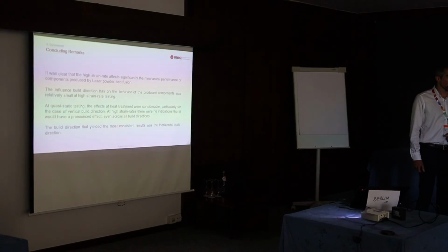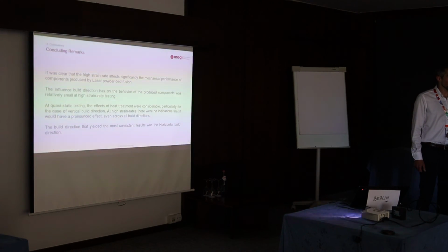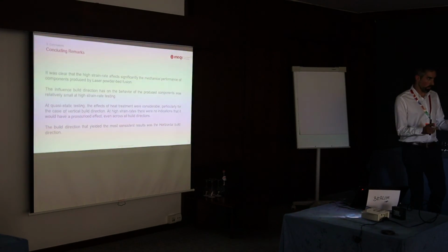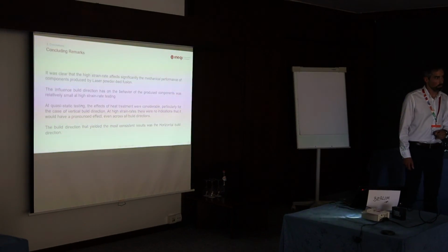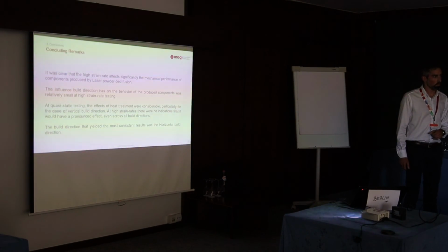Thank you. In my opinion, another way to really look at the strain rate dependency of a material is to do a simple tensile test with a machine where you can vary the strain rate during the test. So you can really see the jump on the same material. Then you eliminate a lot of factors with different samples. But would you be able to go from quasi-static to such a high value? I'm not sure how much higher, but it gives a fair indication. Let's say I go from 10 to the power -6 to 10 to the power -1, so 5 orders of magnitude of difference. And then if there is sensitivity to strain rate, you will be really able to pick that up in that range, and that will give you a clear indication, and then you can go for this kind of high deformation. Thank you.